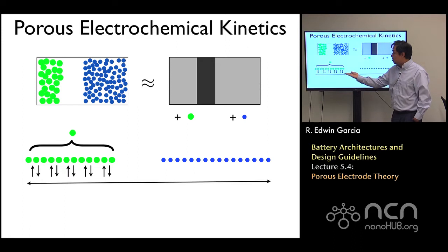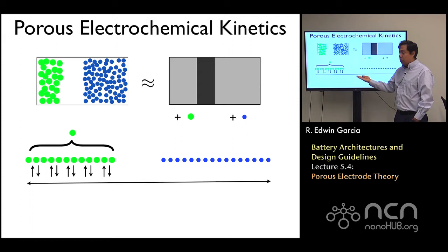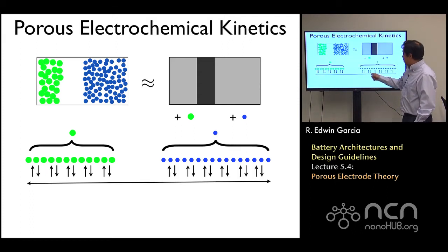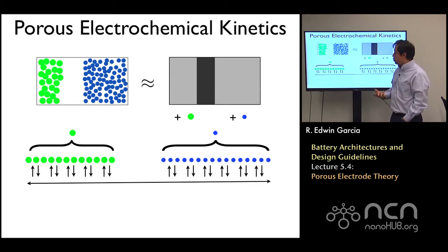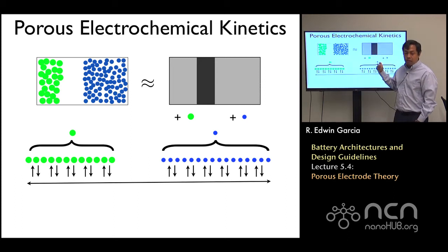That diffuses through those electrochemical equations that we just described, and then through those electrochemical gradients we have mass transport, in this case in the anode section and in the cathode section, and the cathode particles will take that lithium back in, allowing us to decouple the problem into two parts. One where we have the transport in the electrolyte alone, where the properties will be just position dependent in those three layers, and the diffusion from the electrolyte into the cathode by defining a representative particle on each phase.